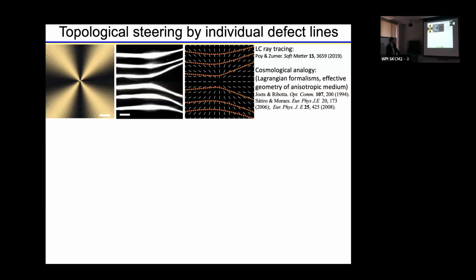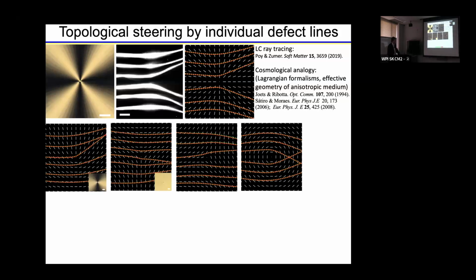The very interesting thing is that you see here two different lines, red and dashed yellow, that totally overlap on top of each other. So we had to plot them in this way. One is dashed but thick, and another narrow but continuous. And they agree with each other. So one is based on liquid crystal optics. The other one is based on cosmology predictions for interaction of light with an elementary cosmic string. And we plot them on top of this pattern, where, of course, we disregard the actual length scales, right? Because for cosmology, those would be light years. For liquid crystals, those hundreds of microns or millimeters, right?